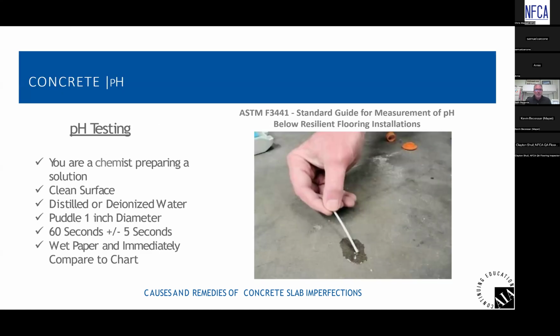So from a testing standpoint, it's pretty simple. You're cleaning the surface, using distilled or deionized water, putting a 1-inch puddle. You could use a pH strip in the puddle of water, and then you're reading that to see what your pH is. Brand new ASTM standard that was released within the past year, something like that, is 3441, which is a guide for measuring pH underneath resilient floorings. Just a standard that kind of gives you the directions on how to conduct that pH test.